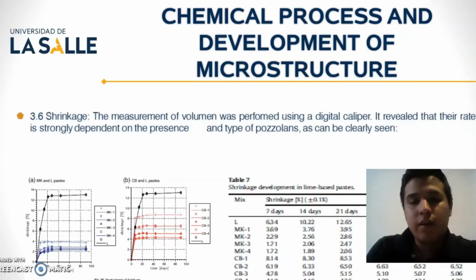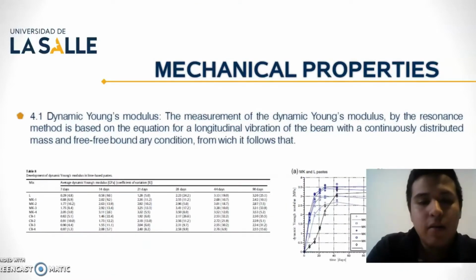The reduced shrinkage in mortars containing pozzolans can explain their inherent strength. The high shrinkage of pure lime matrix pastes causes microcracking around aggregates, and the presence of the cracks causes strength and stiffness reduction as reported. The observed early stiffness gain in the paste containing pozzolans is probably coupled with the early strength gain, in agreement with the conclusion reported in the literature.